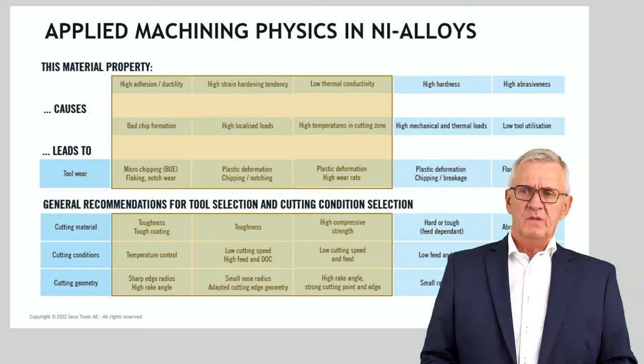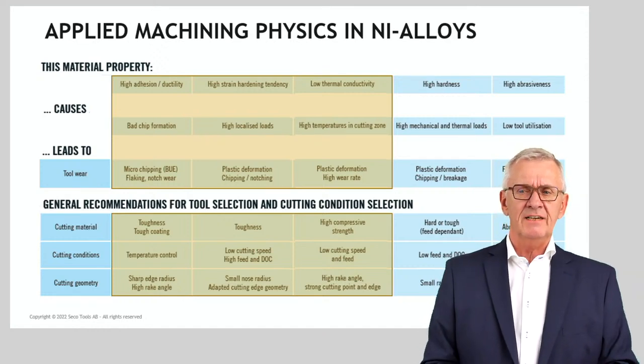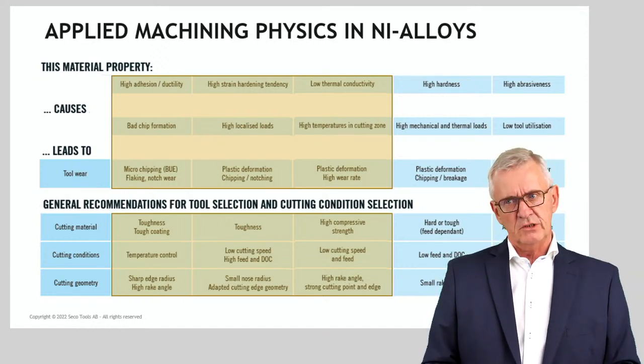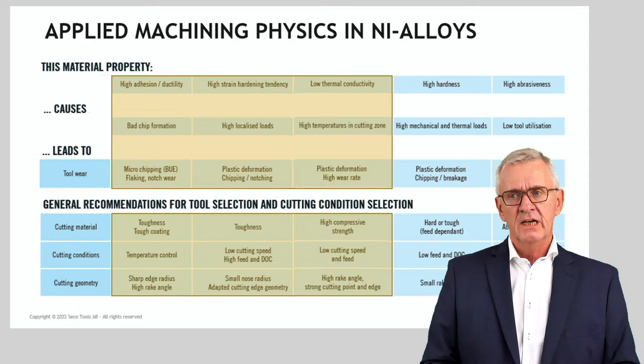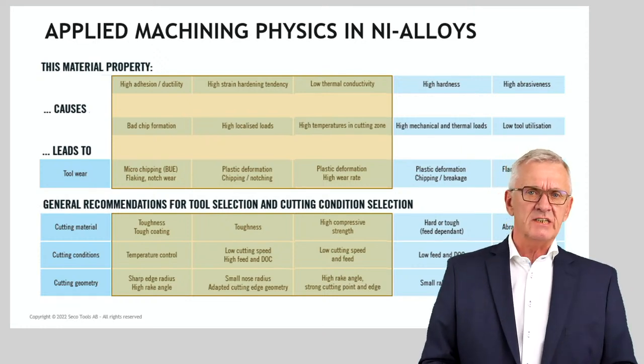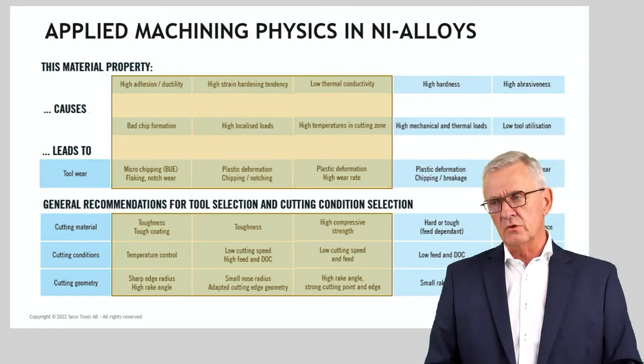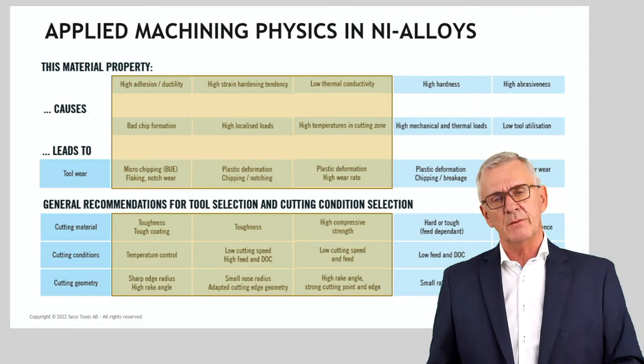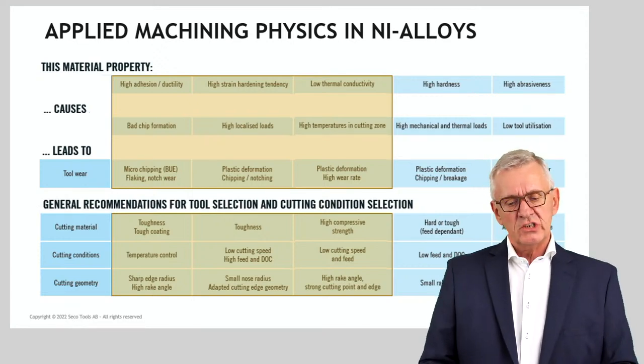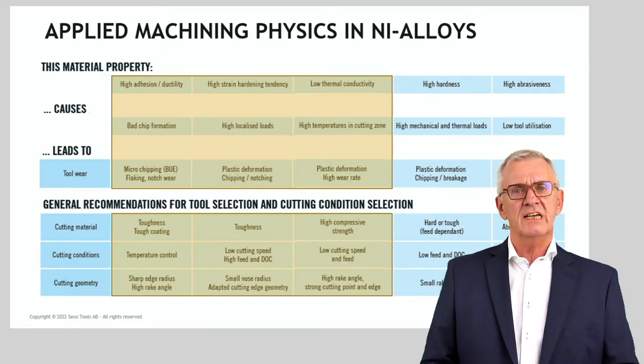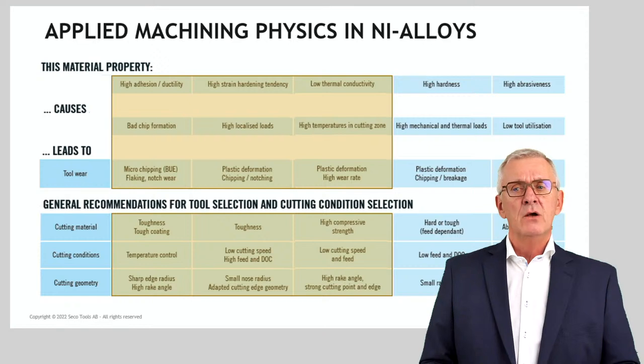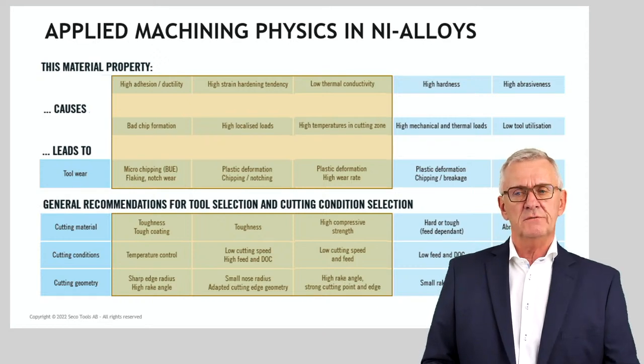That means, coming a bit to a conclusion, that these five properties we talked about very, very fast: the adhesion, ductility, the strain hardening factor, the low thermal conductivity, the high hardness and the high abrasiveness. Those things cause certain things to happen during machining, which would lead to a very specific tool wear.